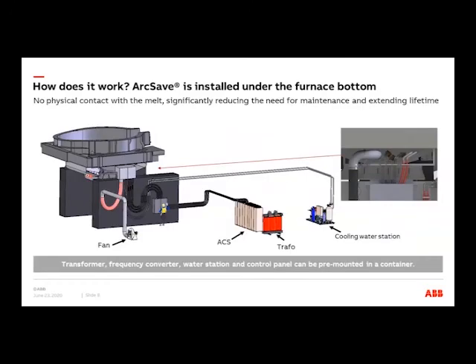So how does this ArcSave electromagnetic stirrer work? The stirrer is installed under the furnace on a cradle with a gap from the furnace bottom. The bottom of the furnace needs to be in austenitic stainless steel, for example 304L or 316L. When we are operating the stirrer, we are creating a traveling magnetic field which penetrates the bottom and the refractory, and generates a stirring force into the liquid metal. The auxiliary equipment is composed, from the right, of a cooling water station, a water skid, a transformer, a frequency converter, and a fan which is blowing air between the stirrer and the furnace bottom. Optionally, a junction box can be put on the foundation for the electrical cables, or on the cradle wagon.